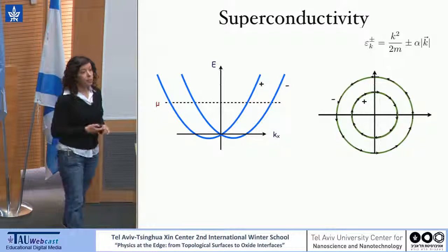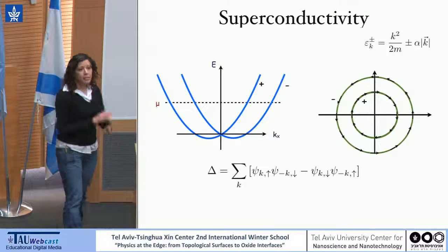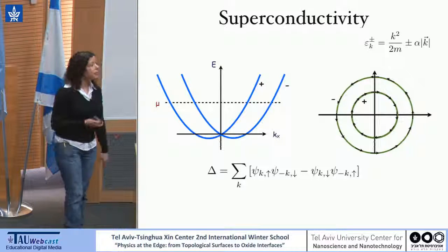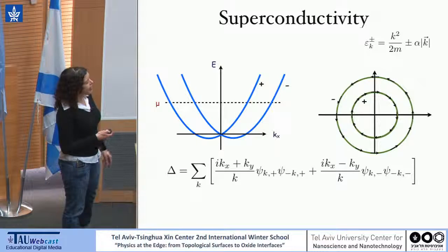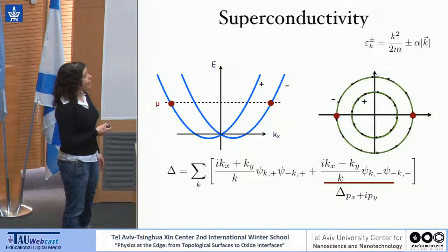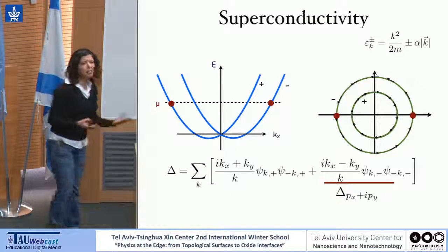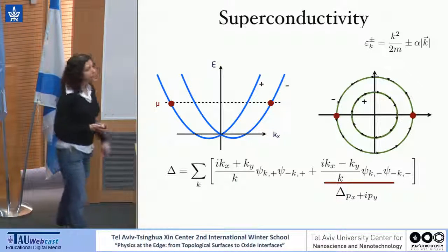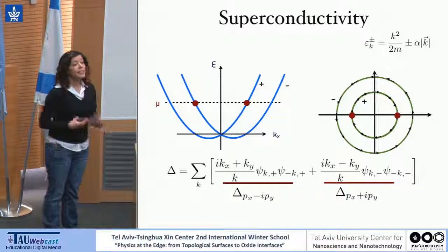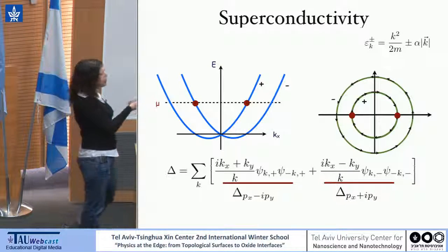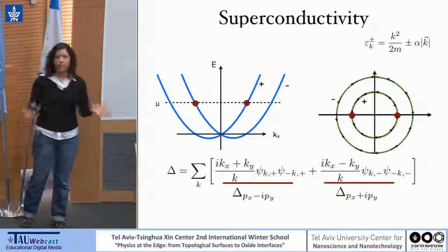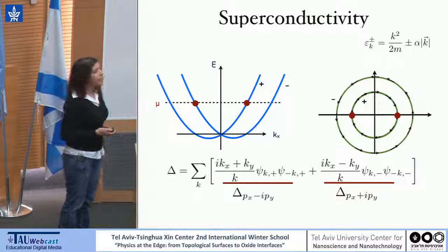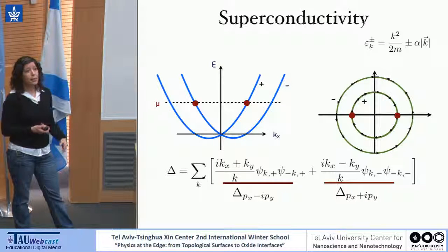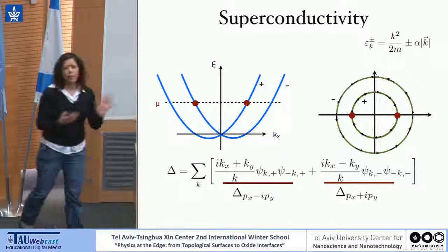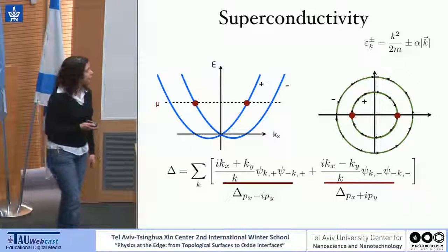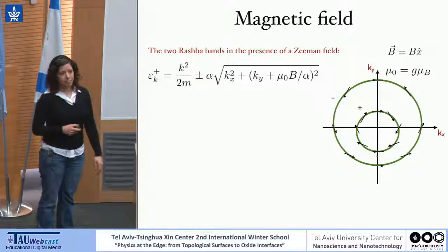Now we can ask what happens when we add superconductivity to such a system. So regular S-wave type superconductivity, in terms of the new band, is basically going to be pairing in the minus band. That looks like a chiral p-wave superconductor, but it's not really important. Pairing in the second band also looks like a chiral p-wave superconductor, but with opposite chirality. So altogether, it's just a regular S-wave, nothing unique in such a system. So as long as we don't have a magnetic field, when we consider the pairing, the spin-orbit coupling doesn't do anything, actually.